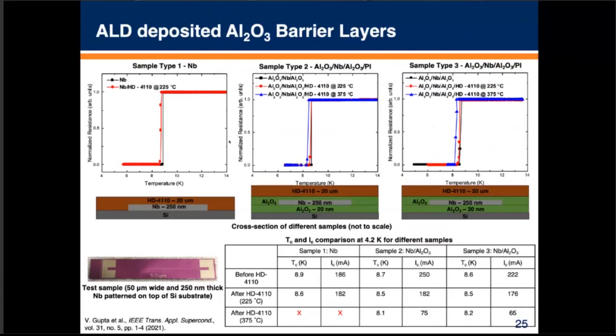I mentioned earlier about using ALD deposited aluminum oxide as a barrier layer. This was just to point out that's something else that has been explored, to look at the ability to cure polyimide on top of niobium with or without these barrier layers, or pushing to higher temperatures. For example, if we didn't use a barrier layer and we tried to cure that polyimide at the recommended 375 degrees C, it completely killed the niobium superconductivity properties. Whereas for some of these other samples, you can see going to these higher temperatures, even though there's a small amount of degradation in the TC and IC, we're still left with significant superconducting properties for these structures.